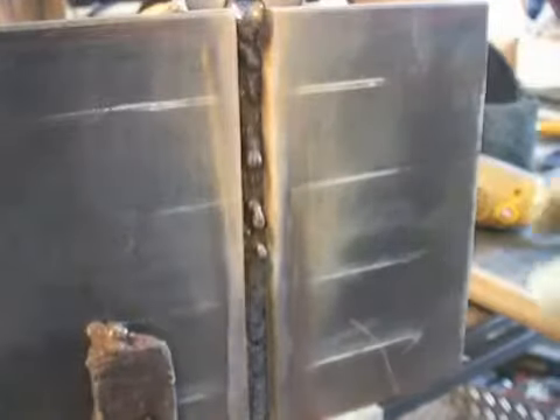All right, here's the tie-in on that. You light up ahead of the tie-in, you come down into it, and then just carry on. That does leave some crap to burn out, but usually it's not a problem unless you hang around a long time and deposit a whole lot of junk. But it's good to deposit any arc strikes like that over an area where you're going to remelt, especially rather than outside the joint. Arc strikes outside the joint are cause for getting failed. Depends on the strictness of the supervisor if they'll let you grind them or not, but oftentimes they're a reason for failure.